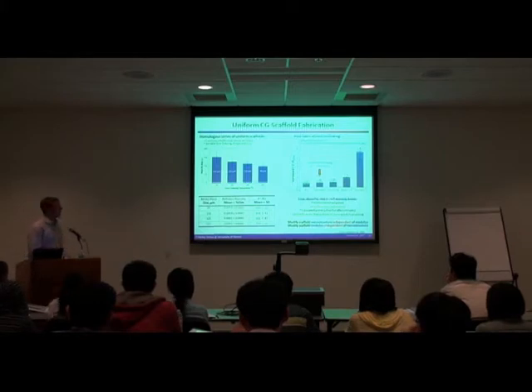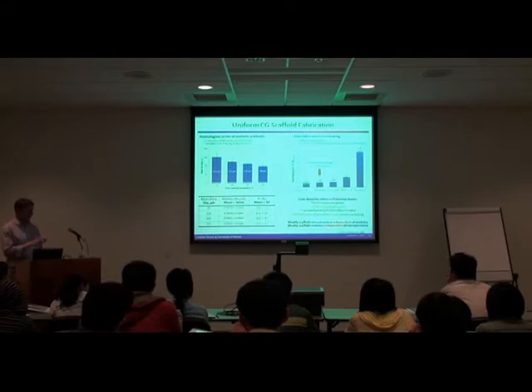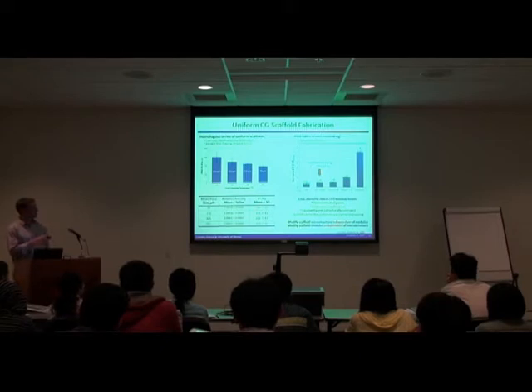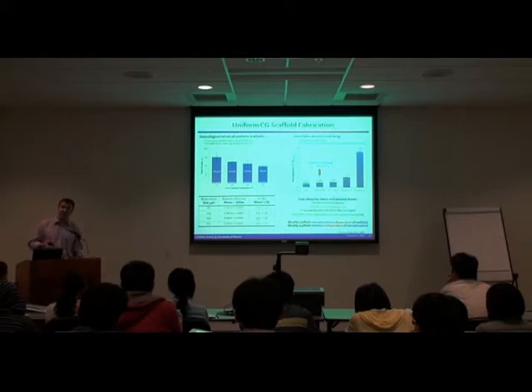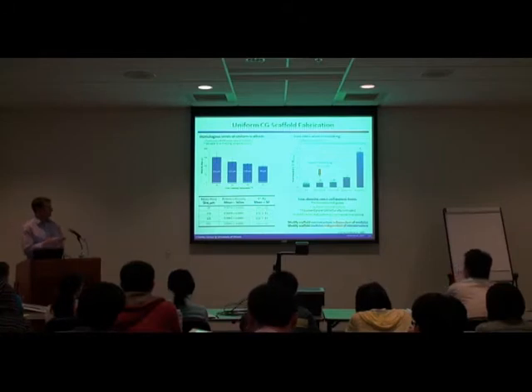And so we have ways in which we've produced a number of different homologous series of our scaffolds, one of which is by changing the freezing temperature. This goes back to the fabrication method I talked about. We can change the pore size of the scaffold without changing its relative density, because we start with a constant suspension, with the same amount of collagen in all the suspensions, and so what you get out is a three-dimensional material that has constant relative density, different pore structures.